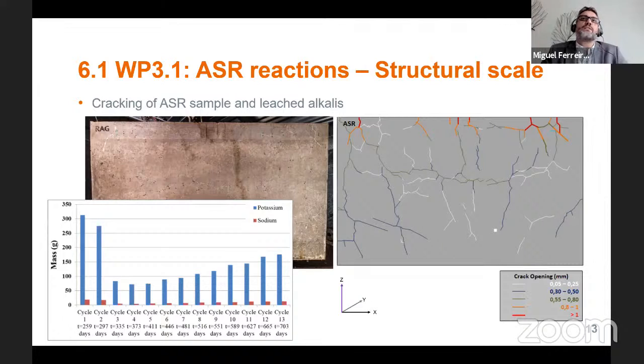And you can see in the beginning, in the first 2 water cycles, there's a very high content of alkalis, and these are obviously being leached directly from the concrete into the water. But after a while, this stabilizes, and only when concrete starts to crack and open up cracks, then do we see again a gradual increase in the alkali content. So as the concrete begins to crack and as the cracks begin to open, there's access to more pathways for water to access and help leach out the alkalis as well.